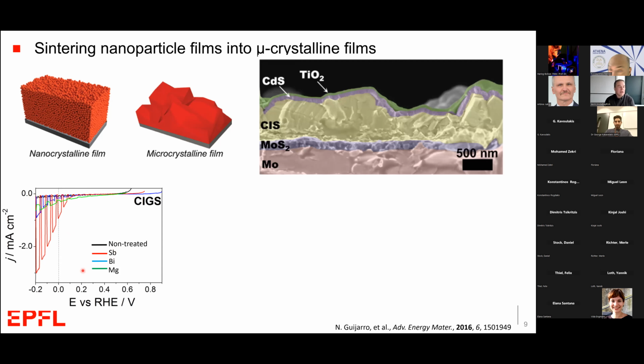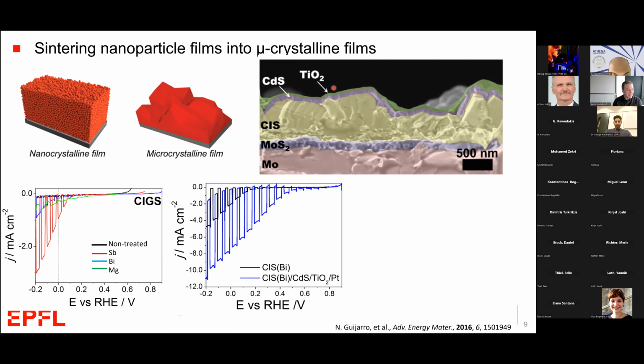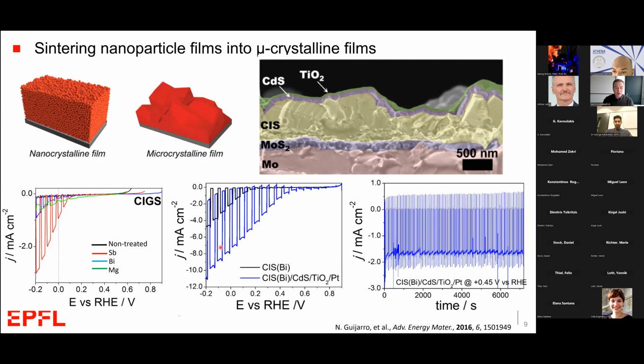Moreover, we can finish the device by adding an electron extraction layer, a protection layer like titanium dioxide, and then a catalyst layer for the hydrogen evolution reaction, and achieve now results in this paper which were very similar to CVD processed CIGS or CIS films, with a photocurrent of about 8 milliamps per centimeter squared at 0 volts versus RHE. So that's like the short circuit current, if you're familiar with photovoltaic cells. Moreover, this device is quite stable for a long operation in the lab and produces hydrogen at a Faradaic efficiency of 100%.